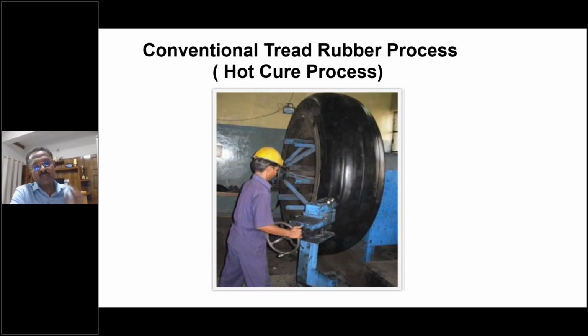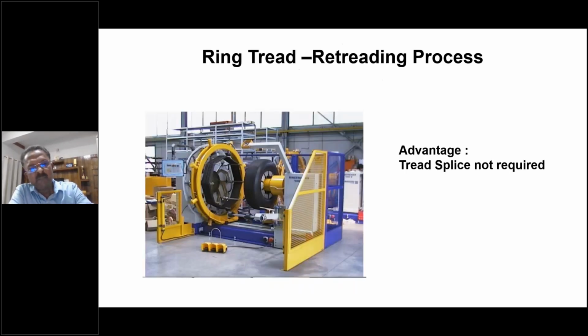In the hot cure process, the difference is that there are no designs. It's uncured material that has not been cured. It's a hot process because it needs more heat compared to the pre-cure process, which is a cold process. In ring tread, the difference is that we place a ring-shaped tread over the tire casing, so no splice is required.